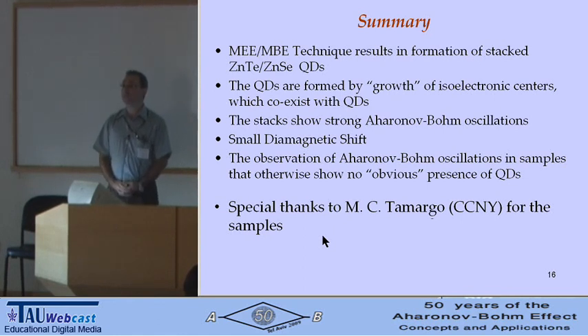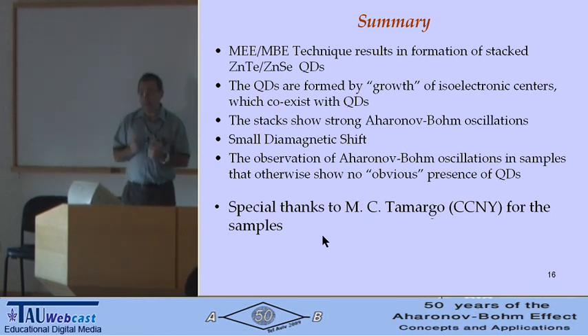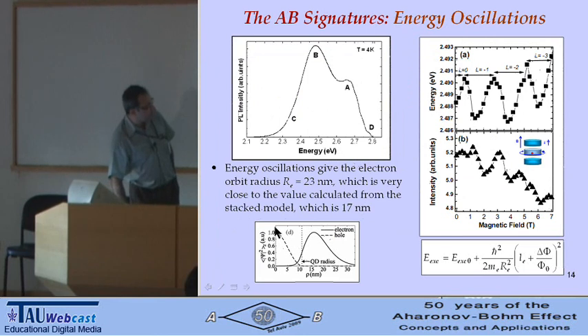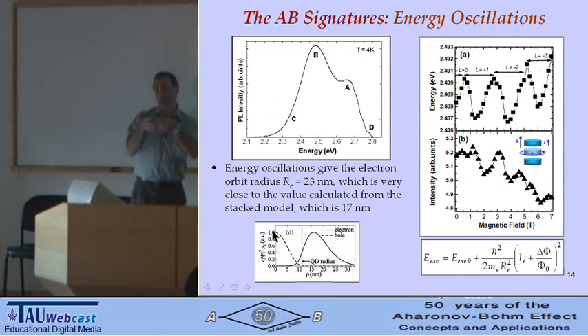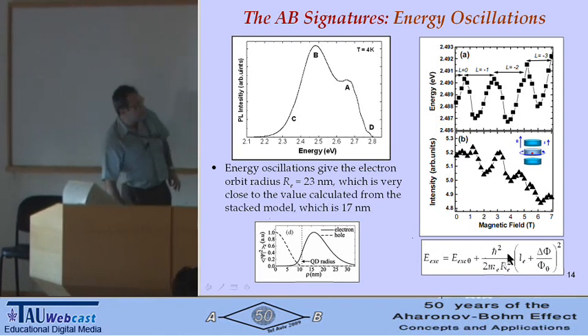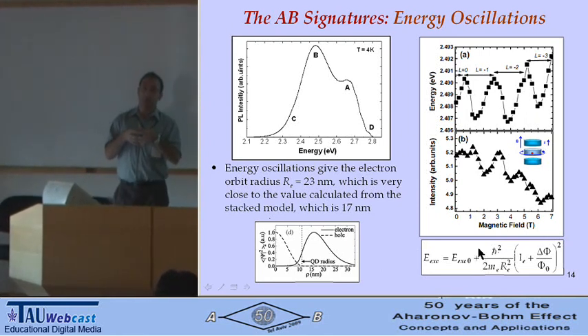To which theoretical limit is your experiment closer? You mentioned the limit of no Coulomb interaction, independent electron and hole, and the opposite limit, the exciton. Is the experiment closer to one? Both. And the reason is we cannot distinguish, because, as you saw in the calculations, in this case the hole is very strongly confined within the quantum dot. So for all practical purposes the hole doesn't move, and what's happening is only due to the electron motion. So assume the radius of the hole orbit is 0. You have to assume that the hole's orbital momentum is always 0. Then you are close to the single-particle condition, because only the electron changes its orbital momentum.